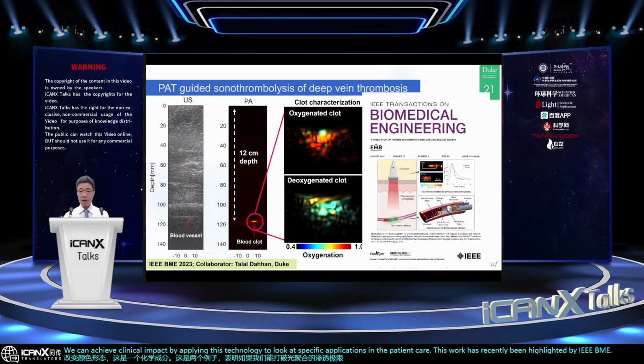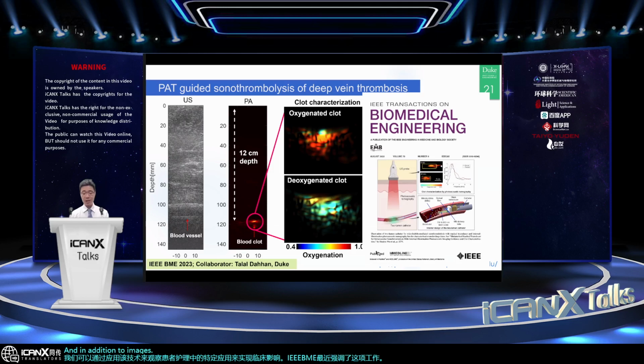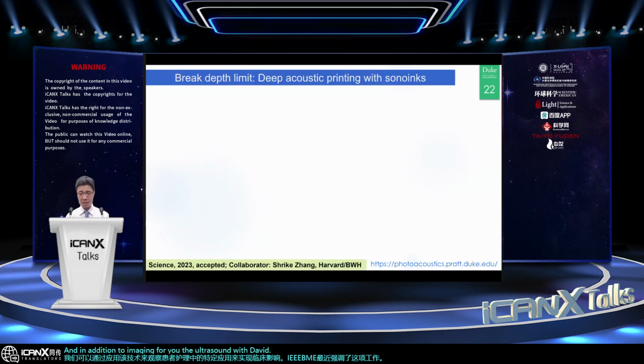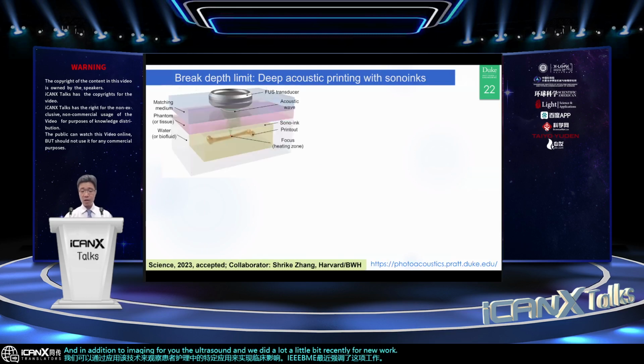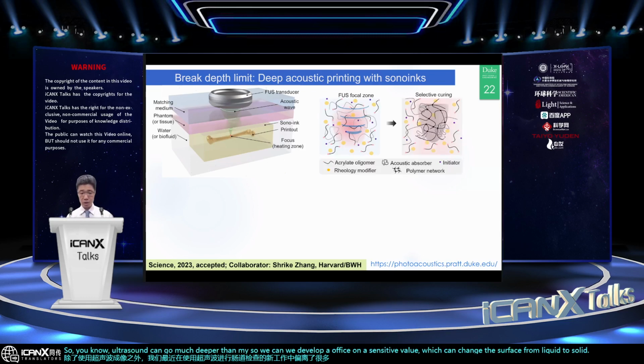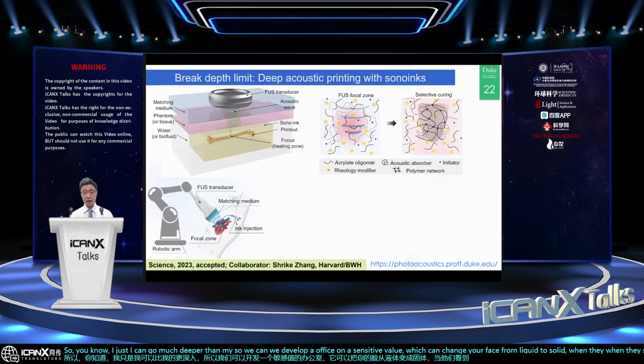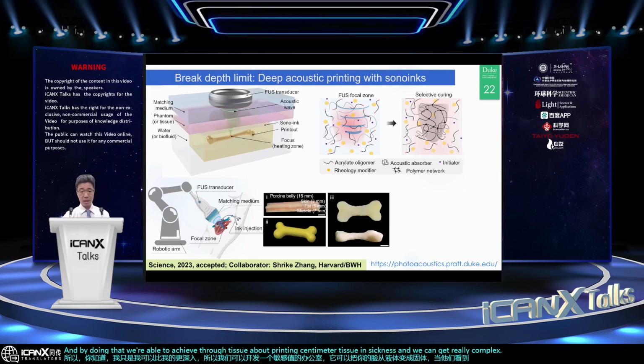And in addition to imaging using ultrasound, we deviated a little bit recently with new work using ultrasound for bioprinting. Ultrasound can go much deeper than light. So we developed an ultrasound-sensitive bioink, which can change its phase from liquid to solid when it sees the ultrasound pressure. By doing that, we're able to achieve through-tissue bioprinting, centimeters in tissue thickness, and we can get really complex structures printed inside or through the tissue.